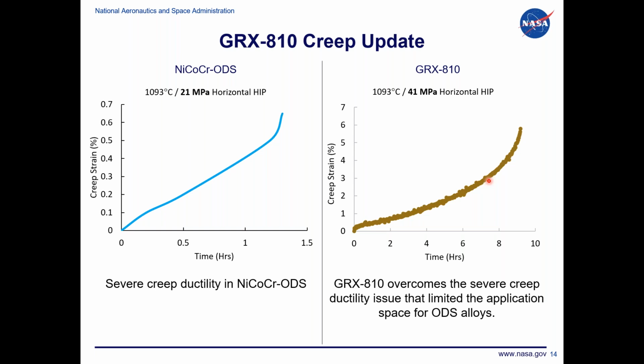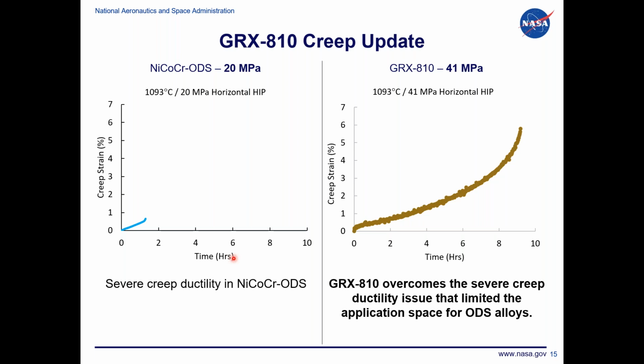So I want to compare now nickel cobalt chrome ODS and GRX-810 in the horizontal orientation. And I want to be clear here, on the left is 21 megapascals of stress, and on the right is 41 megapascals. So in the GRX-810 case, it's double the stress as compared to just nickel cobalt chrome. And then if you look at the X and Y axis, maybe I'll go to the next slide to better compare it. What's interesting is that the nickel cobalt chrome ODS, again, is struggling with that severe creep ductility issue that you expect to see with ODS alloys. But GRX-810 appears to have overcome this ductility issue that has limited ODS alloys in the past. You have good creep ductility, and just comparing this nickel cobalt chrome ODS to GRX-810, it has significantly better life, much better ductility, and we're in an environment where this is double the stress as the nickel cobalt chrome ODS.